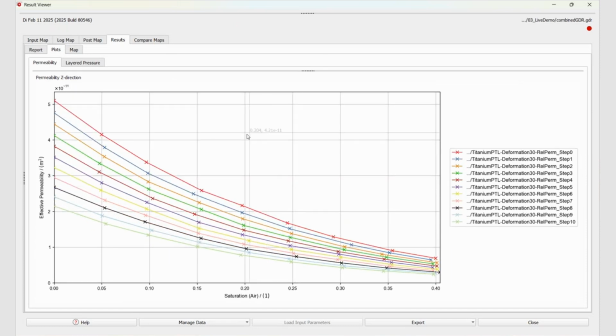So for example, for the through-plane direction, we now have here 10 curves. The red one here is step 0, the uncompressed. We have air saturation from 0 to 40%. And then if we go up with the compression level, we move down here. So that's then the function for the 30% compression, and here then up to 40% air saturation. So you could also plot that maybe in 3D. With the saturation on the x-axis, the compression on the y-axis, and then on the third dimension the permeability. So you get some kind of this shape, and this function you could plug into some upscaled model, and you have the behavior of this material under compression and for different saturations.